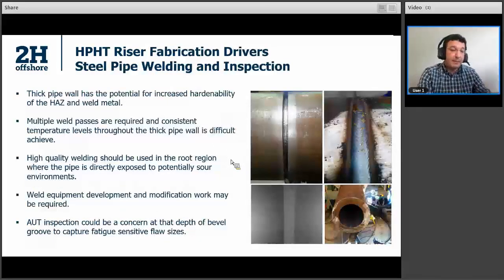Okay, next one is fabrication and inspection. After the pipe is manufactured, the pipe joints need to be welded. Welding is challenging, especially to meet the hardness requirement. During welding, you introduce additional heat on the thick wall pipe, and that will make your pipe harder, which means that your hardness will go up. And it is challenging to meet the hardness requirements dictated by NACE. Second, since the pipe wall thickness is very high, it requires multiple weld passes, as shown in this picture here on the left below.